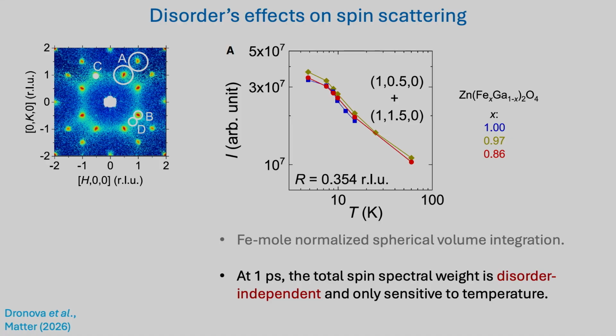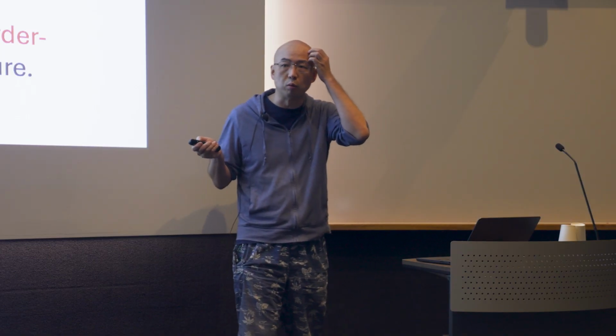Now we actually can do a much better job by quantitatively doing an integration. Here's a scheme about how to integrate the reciprocal space: A, B, C, D, different schemes. We look at scheme A first, which is a large volume integration covering almost all the spin intensities. You can see for all three samples, if you normalize by the mass and mole of the iron, they are identical to each other. To me, this is one of the most surprising parts, because you realize that with the presence of disorder, at 1 picosecond, spins don't see it. The dynamics of spins is only controlled by the temperature, but not by the disorder itself. The time constant at least is not changed.